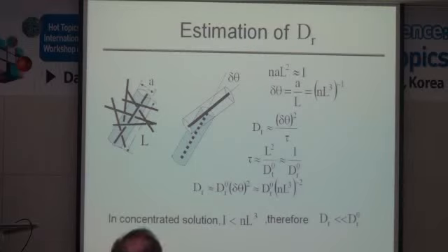You can regard the smallness of the rotational diffusion constant as saying that the effective rotational friction constant in a concentrated solution has increased dramatically, by this factor (nL cubed) squared. That is, for the rod to rotate, it has to travel. It has to make a long traverse. It can't rotate directly. It can rotate by traveling a long way, by repeating this process.